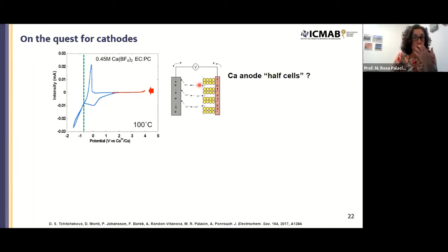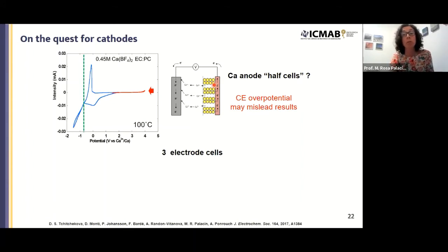If we were working in the field of lithium ion, we would simply test our potential materials against lithium metal, in what are termed half cells in this field. But in our case, I have told you that the calcium anode is an issue and has a lot of polarization. So this is not really a cell setup that you can use, because it would not be reliable. This calcium counter electrode may mislead the results and you will not be sure in which potential window you're testing your material. So you're forced to use three electrode cells.